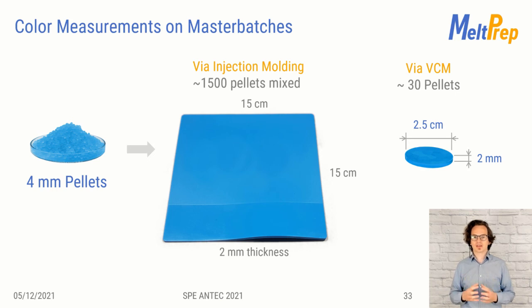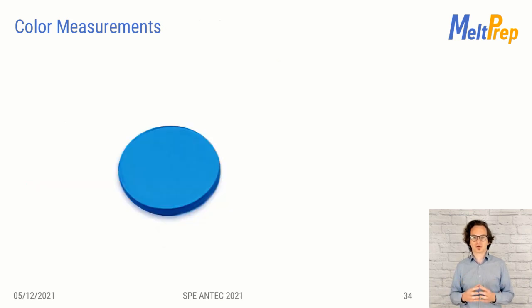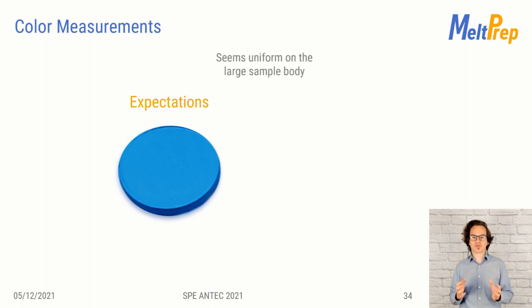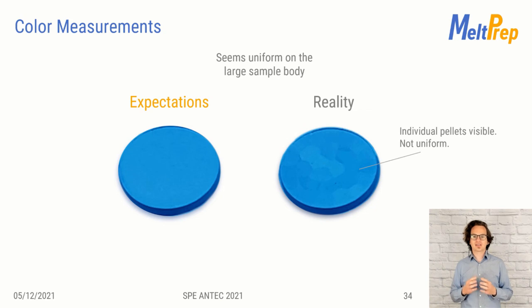Another point is the material uniformity in the sample. We do expect a high uniformity once the pellets are fused together. And the large sample itself seems to have a uniform texture. But we have to consider that this is the case because thousands of pellets were mechanically mixed in a molten state. They were just molten and then injected through the gate into the cavity.